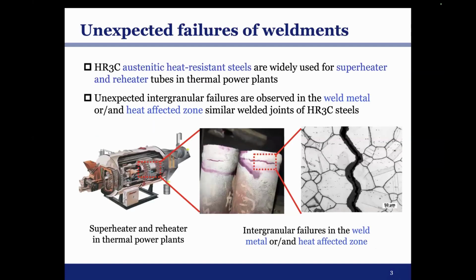In fact, we perform this work because our industry partners found that in their superheater and reheater in power plants, there are some unexpected failures of the weldments. These weldments are used to join the heat resistant steel tubes. And after careful examination, they found that these failures are due to intergranular cracking.